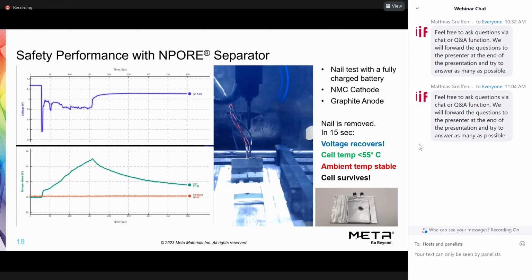First, note that the graphs for this test run for almost 7 minutes. The blue voltage line drops, but then partially recovers. When the nail is removed, the voltage rebounds to about 4 volts. The cell temperature never exceeds 55 degrees, and the ambient temperature remains stable. You can see the hole through the cell, but it continues to operate. There is no risk of propagation to adjacent cells.